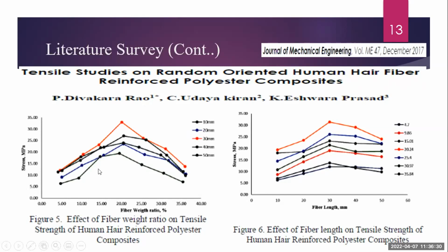strength test. But they changed the fiber weight ratios to find out the tensile strength of the human hair reinforced polymer composite, and in another sample they changed the fiber length to find out the tensile strength of human hair fiber reinforced polymer composites. From that test, it can easily be seen that the fiber weight percentage of 20 weight percent with 80% polymer is giving the highest results in their work also.